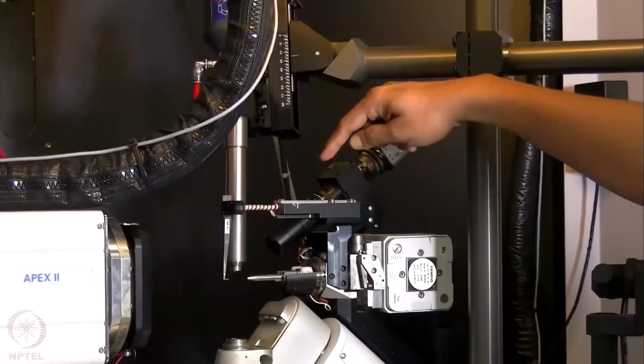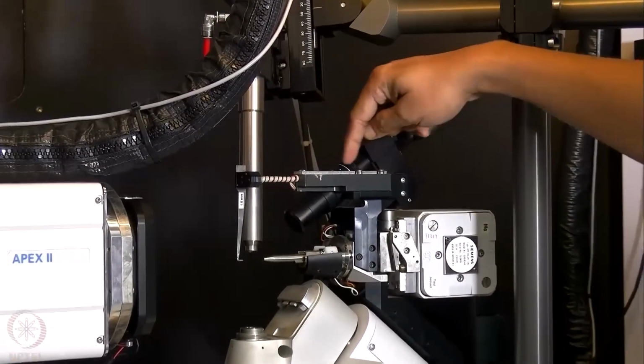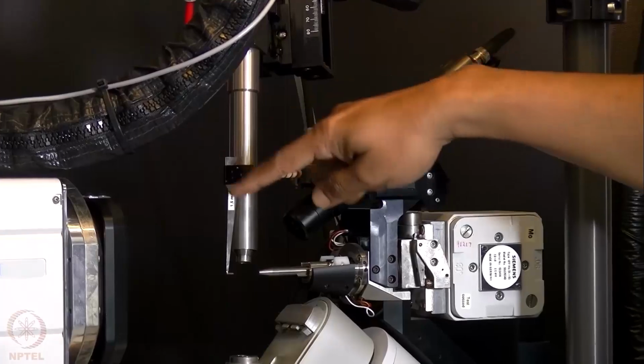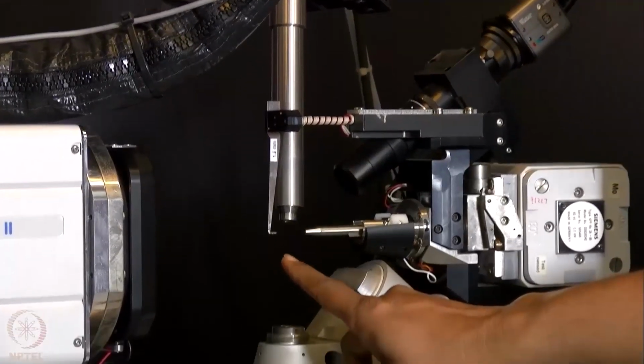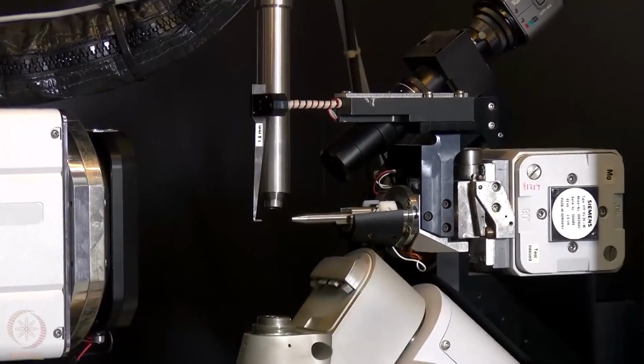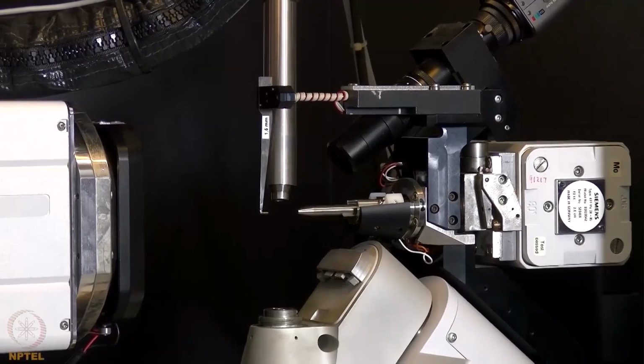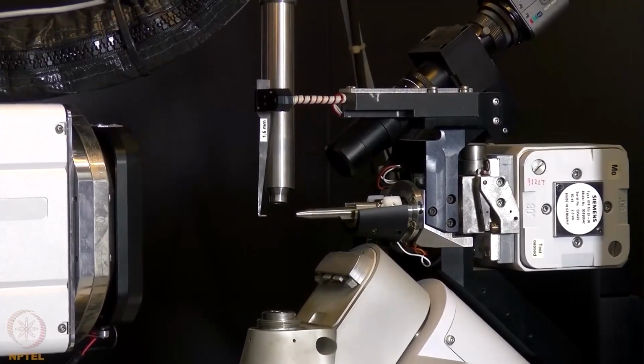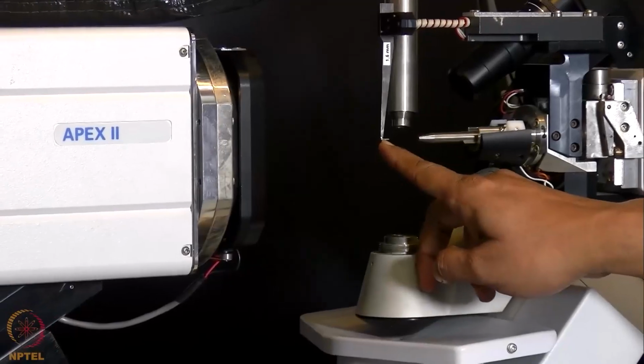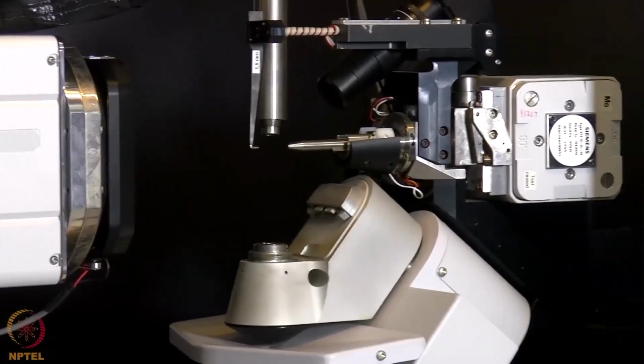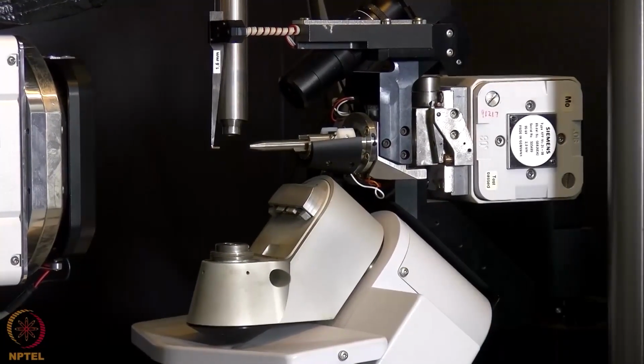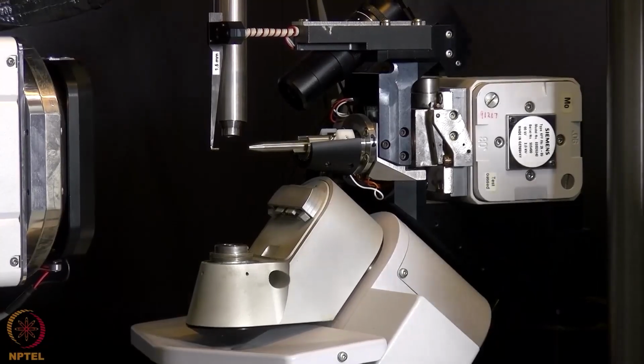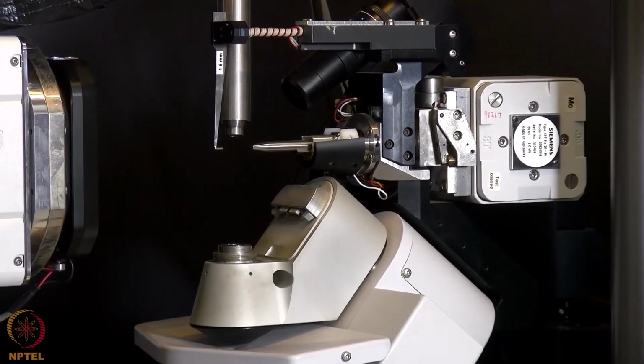Now you can see here the beam stop is mounted directly on this holder, and this beam stop is now exactly in front of the direct beam, so that the direct high intense beam is blocked by that particular piece of metal, which is then not allowing the X-ray beam to go and fall on the detector.